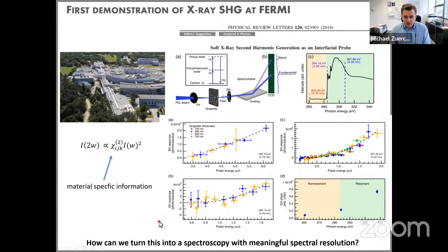So one caveat with this very first work is that at the time the researchers were able to collect 3 photon energies, so 3 data points across the absorption edge, and they could see that there are some non-resonant and resonant effects, as they call it. So they basically said, okay, whether or not you're in resonance, if you're not in resonance with the edge, then you don't see much second harmonic.